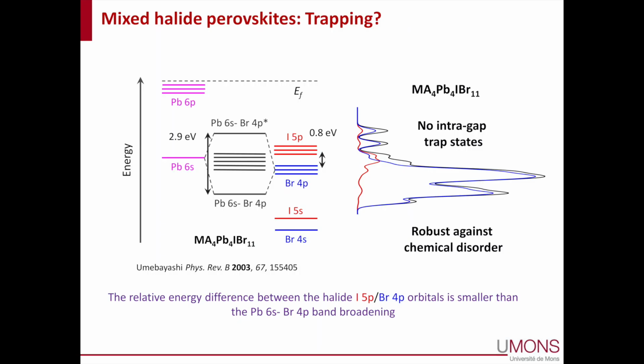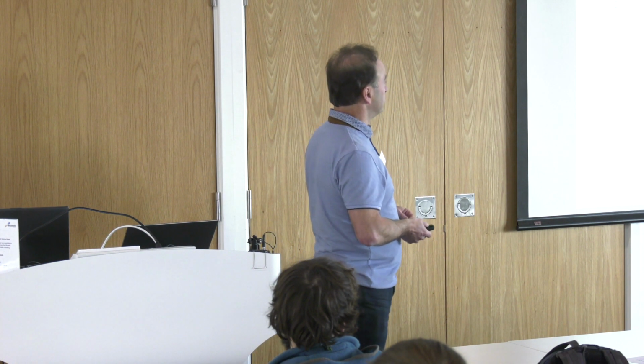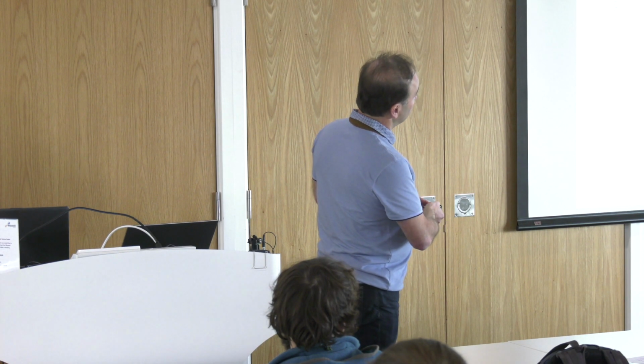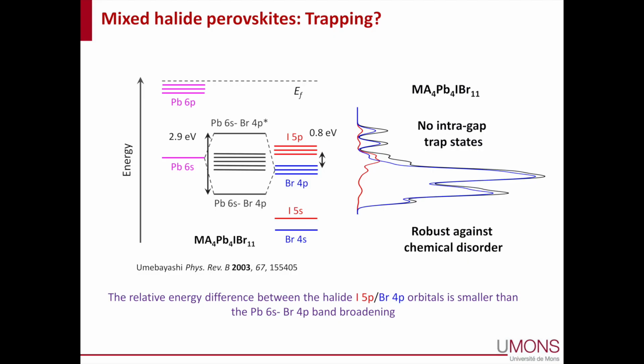And what happens when you introduce iodine 5p orbitals, because they have, of course, lower ionization potential? You might expect those to create traps, to act as impurities that would sit in the middle of the band gap. That is not the case, because essentially this energy level difference between the bromine 4p and the iodine 5p is smaller than the hybridization between the bromine and the lead. So this strong hybridization is one of the key features of those perovskites, and that's why they are rather robust against all sorts of disorder.